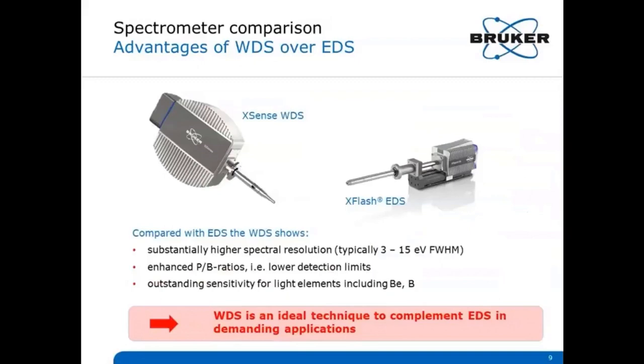As WDS and EDS actually measure the same physical property, it is important at this point to realize that there are some main differences between the two techniques. These are, first, a substantially higher spectral resolution of WDS compared with EDS. Typical values are in the 3 to 15 electron volts range. So that means 10 to 20 times better than EDS.